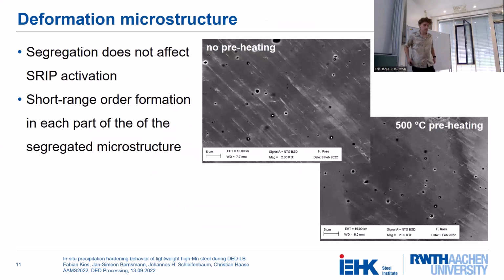Okay, and another important effect in this alloy is again this SRIP effect. And compared to conventionally produced material, you have a segregated microstructure, and we were also interested to see if the segregated microstructure somehow influences this SRIP behavior. And it does not. This is a sample after tensile testing without preheating and with 500 degrees C preheating. And all these lines that you're seeing here are shear bands, which are formed from the planar glide of the dislocations. And I don't think it's very clear in this image, but a couple of segregated zones are definitely going through this image here, and you cannot really see an interruption in the SRIP formation,